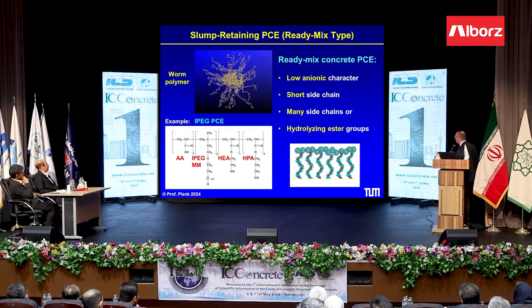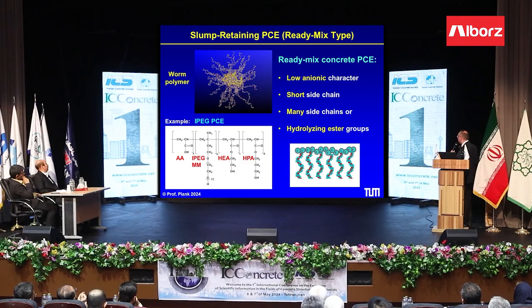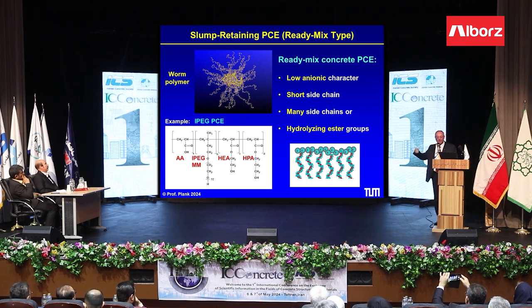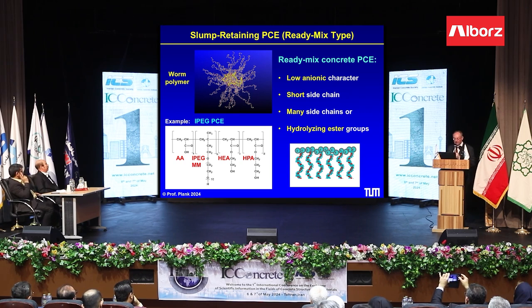Then a slump-retaining PCE, which is used in ready-mix, has many side chains, as you can see here, not so many carboxylate groups. Nowadays we also use hydrolyzing esters in the PCE, hydroxyethyl acrylate and hydroxypropyl acrylate, because they give super long slump retention. You can reach 3 hours, 4 hours of slump retention. And in some countries like China, this is very popular.